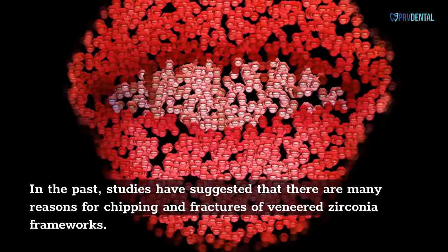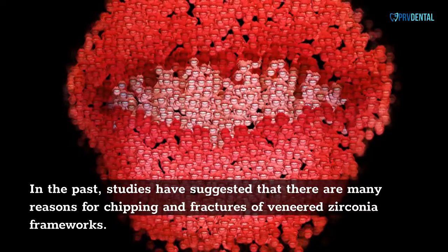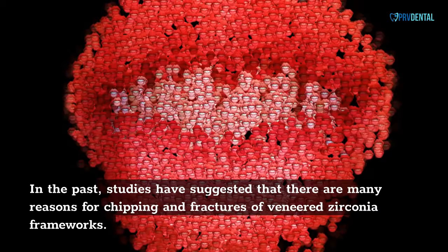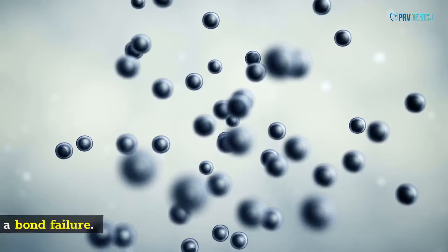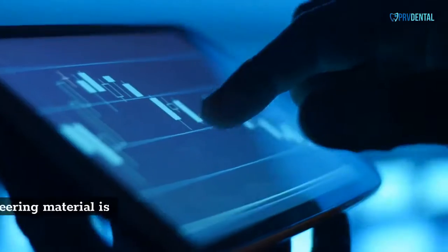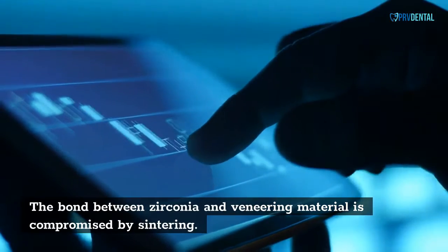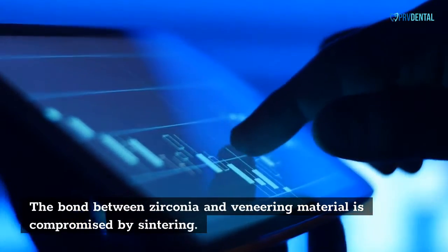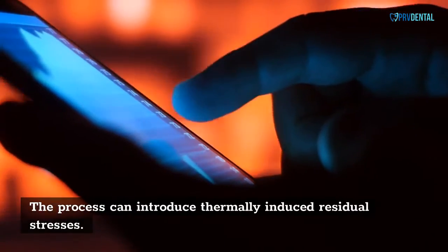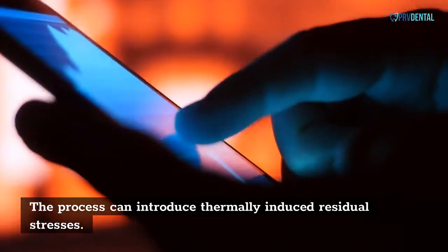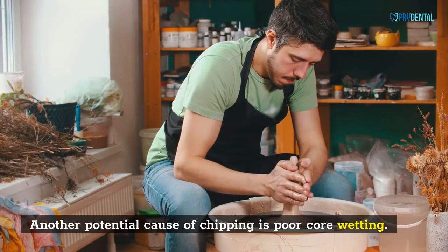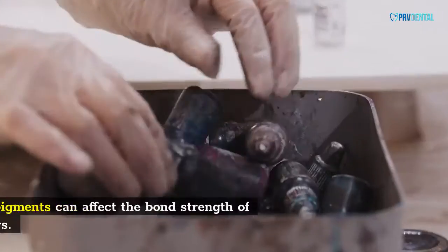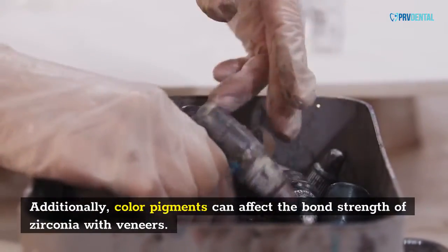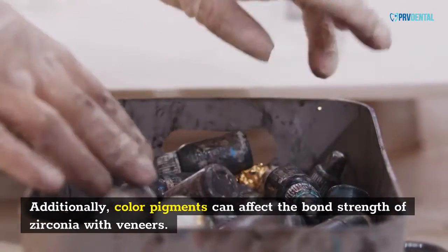In the past, studies have suggested that there are many reasons for chipping and fractures of veneered zirconia frameworks. One of these is a bond failure. The bond between zirconia and veneering material is compromised by sintering. The process can introduce thermally induced residual stresses. Another potential cause of chipping is poor core wetting. Additionally, color pigments can affect the bond strength of zirconia with veneers.